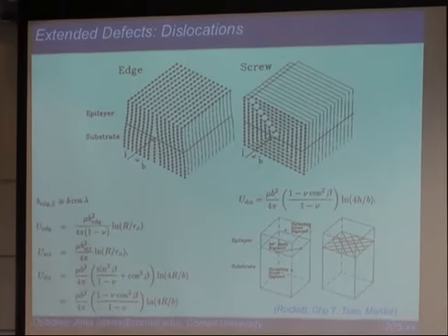And it's visually clear that you can actually have one missing broken bond here, right? One line of atoms that will be a broken bond here, an extra plane. So this has a smaller lattice constant, this is larger, so essentially it will conform, but there will be an extra plane, let's say, as an example. And that's one kind of defect. And again, we had briefly discussed the vector, which says, how do you find where the defect is? If you have done a TEM image and it's not very clear, sometimes it's very hard to pick up the defect even in a TEM image. Sometimes you can, but sometimes it's very hard.